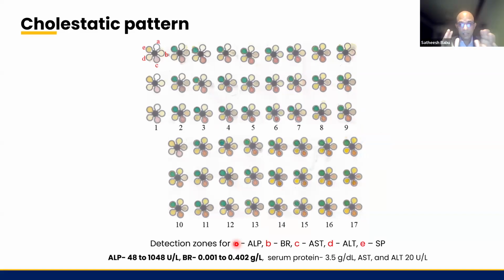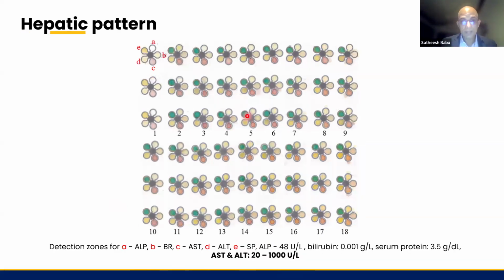We typically looked at two patterns. One is a cholestatic pattern wherein alkaline phosphatase and bilirubin concentration change. Most of the other things will not change much. So with the help of the clinicians, we were able to fix the range of concentration needed, and we have tested successfully for these two. Alkaline phosphatase and the bilirubin we tested, keeping all other analyte concentrations constant. Likewise, we tested another pattern, the hepatic pattern, where AST and ALT concentration change, and the others may not change much in that condition. So we focused our study only on these particular analytes.